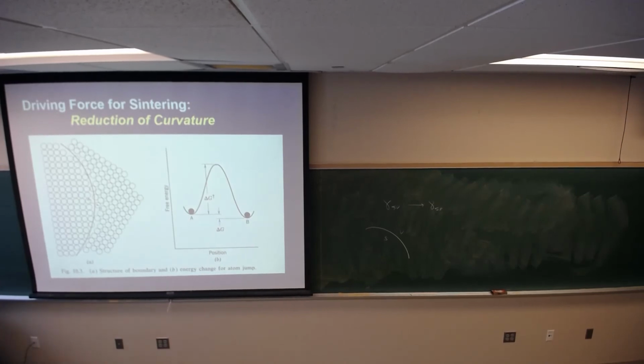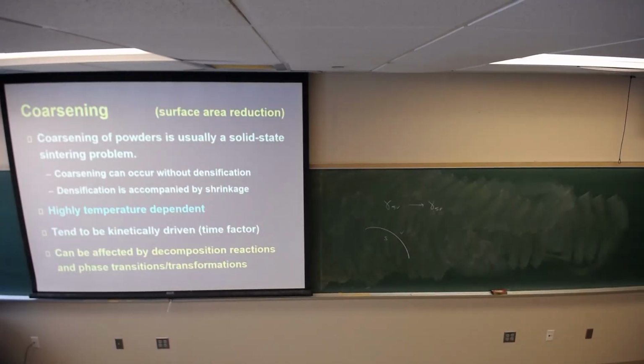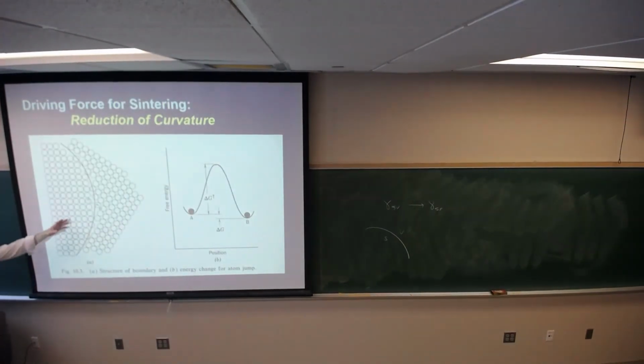Okay, and that is by and large everything you need to know about sintering. If you increase the surface area, you increase surface energy. Then it's a greater driving force to reduce that surface energy by doing a couple things. One could be coarsening. Okay, so in the initial stage of sintering, by the way, this is an argument for free energy. You could argue, though, that this is actually an argument for grain growth rather than an argument for sintering.